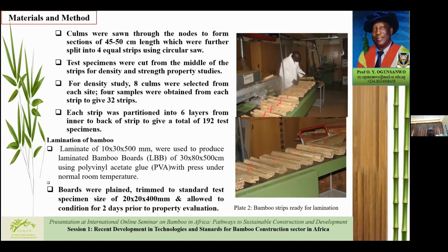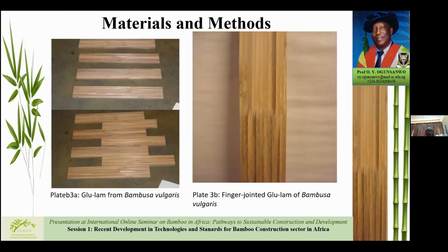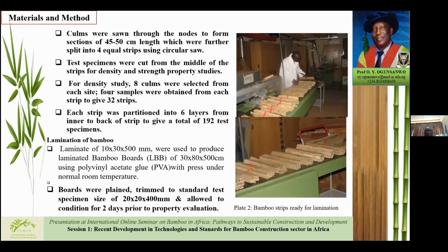to give a total of 192 test specimens. Lamination procedure involves the production of 10 by 30 by 500 mm laminae, which were used to produce a laminated board. Those laminate members were combined in various forms to form the laminated bamboo board of 30 by 80 by 500 cm using the PVA with press under normal room temperature. Culms of this bamboo were trimmed to standard specimen of about 20 by 20 by 400 and allowed to condition for 2 days prior to the test.